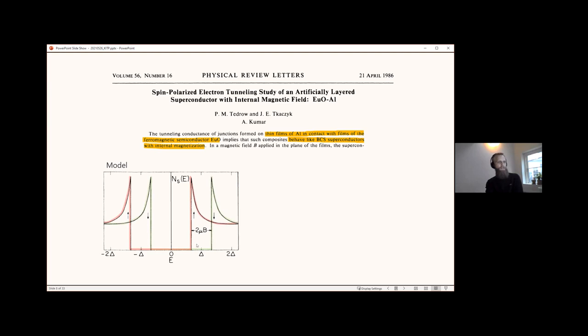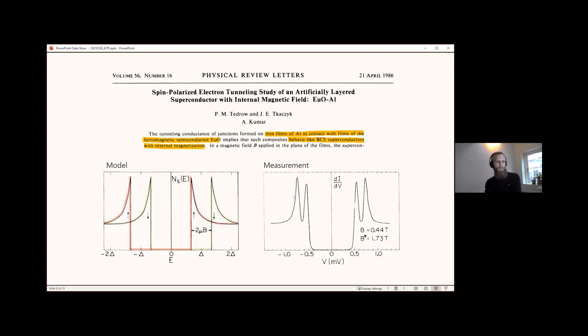And that's what they did. They measured the tunneling spectroscopy of the system, and at finite applied magnetic fields, they found that the effective magnetic field greatly exceeds the applied field, basically by measuring the splitting of the coherence peaks.